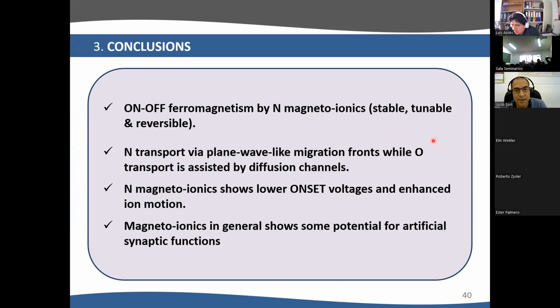I've shown you that this can be done both with nitrogen transport or oxygen transport, that the nitrogen transport is via plane wave-like migration, which creates like bilayers, which is interesting. And also nitrogen is faster and with lower onset voltages than oxygen ion migration. And in particular, if you do dynamic effects, there are some functionalities that can mimic some of the properties of the brain.